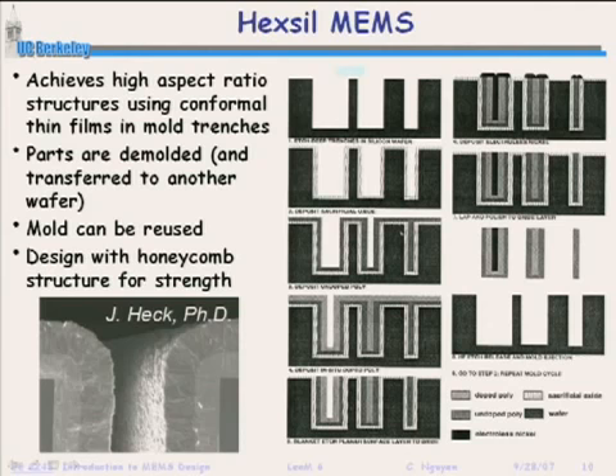In this case, you're using a deep reactive ion etch to etch these deep trenches that are actually creating a mold. So this now serves as a mold for the actual structure that you want to make. What they do after this, they deposit a sacrificial oxide, they deposit an undoped polysilicon, then an in situ doped polysilicon. Then to make it more conductive, they can put nickel in here using an electroplating process. This is an interesting electroplating process because it's electroless nickel. You don't need an electrode to do this. So I'm telling you now it's possible to actually plate nickel this way. But then what they do is they dip this into hydrofluoric acid to remove all of this oxide here.